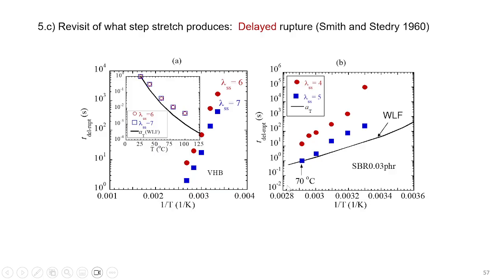And we repeat for the first time the result of Smith and Stedry about how you stretch to the same level at different strains and wait for the delayed rupture, how the temperature dependence occurs, and the dependence is very different from the WLF. This is just being submitted as a paper.